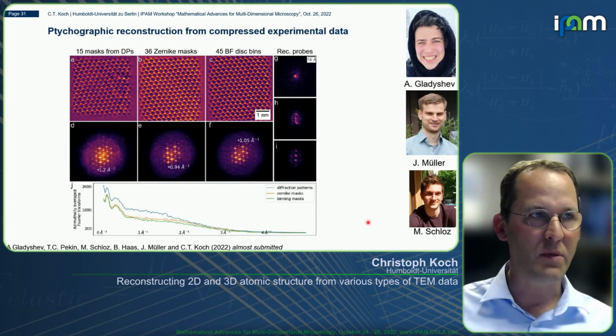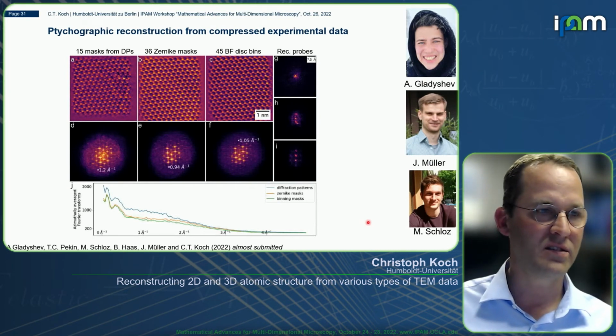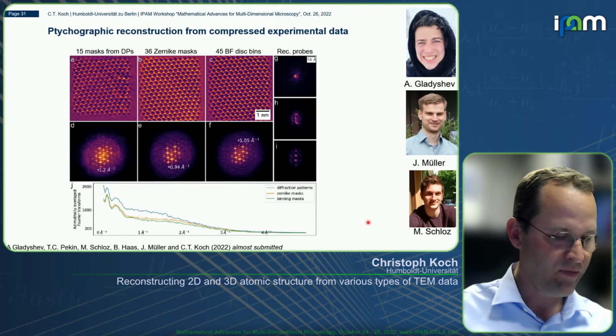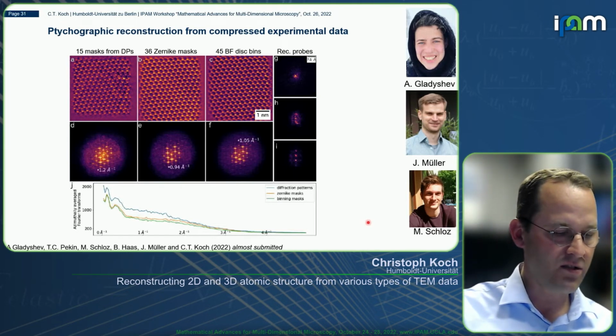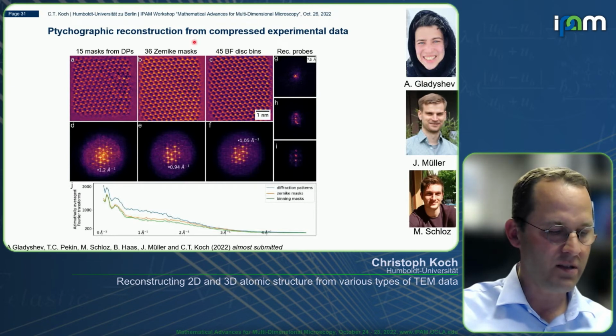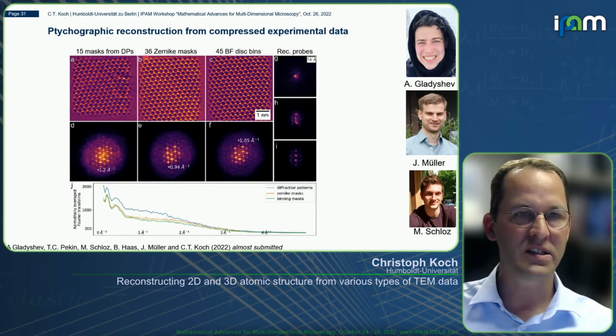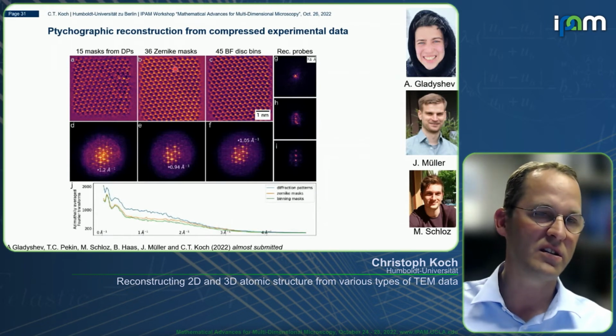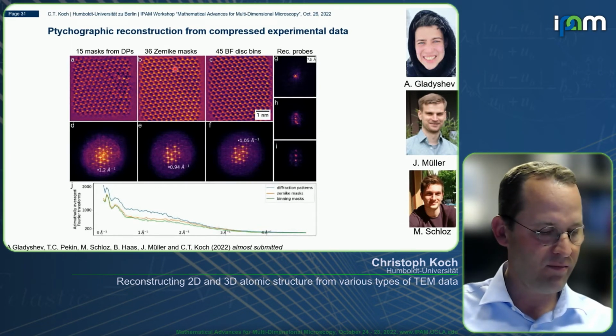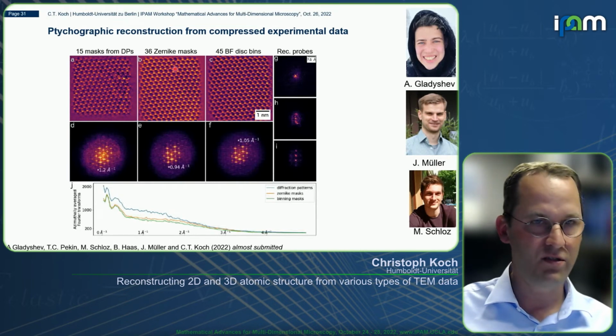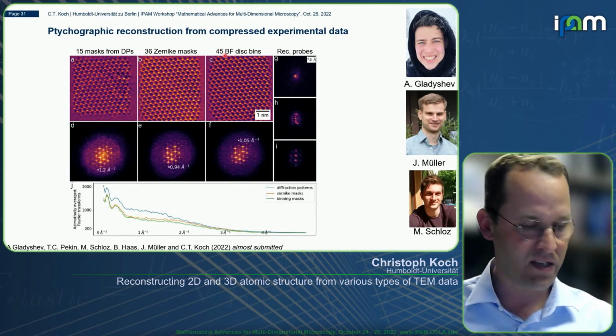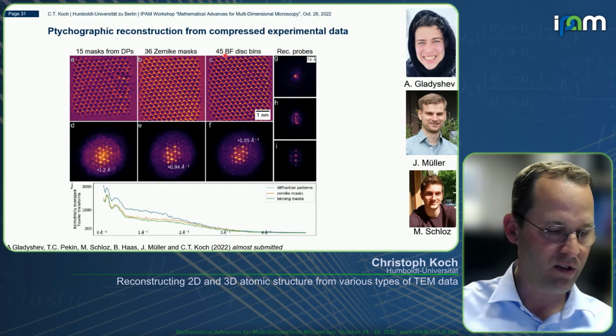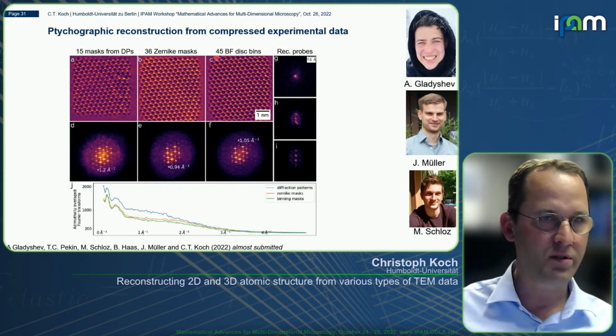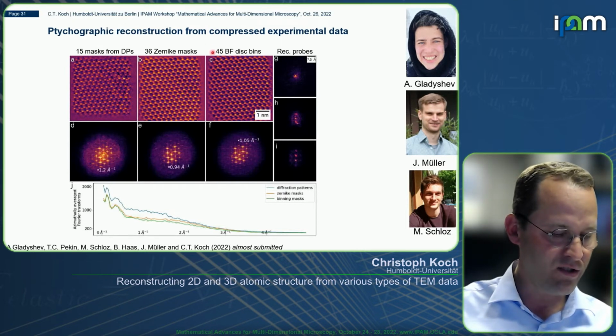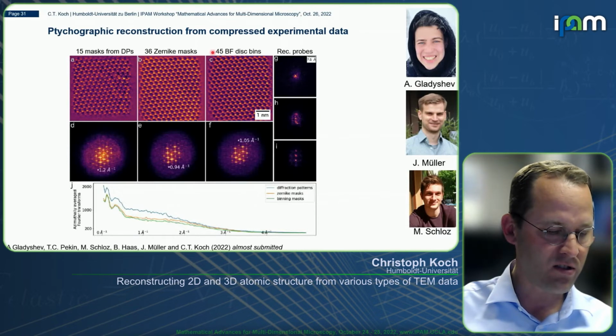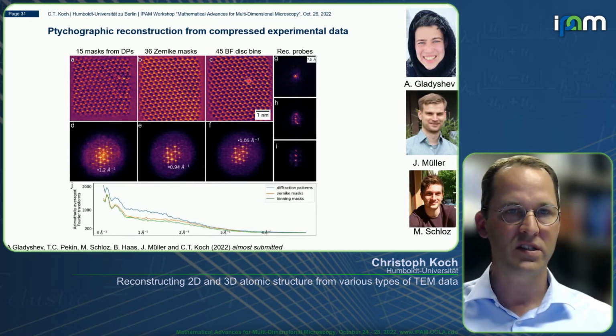And this is now applying this also to experimental data that was acquired on the Spectrus detector on our microscope, trying different ways to compress the data. So this is basically what was shown in the simulation, 36 Zernike masks being applied to the diffraction patterns and then only storing the mask applied to the diffraction patterns. Or here, reducing, basically doing the binning approach that was applied in this data by Dave Muller's group, using 45 numbers per bright field disk, led to reconstructions where you could see really the atomic structure of the unit cell, but you didn't see any variations between unit cells.